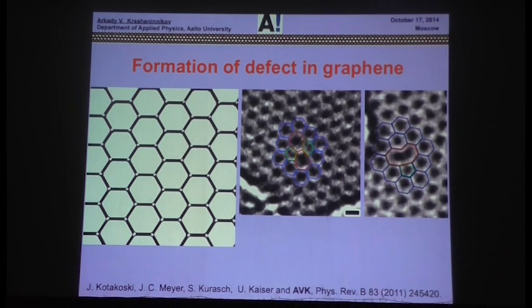Another important issue is that electrons not only knock out atoms. When you are close to the threshold, very interesting effects may happen. For example, in graphene, you may get a vacancy here, a reconstructed vacancy, where one atom is missing. You can also get the so-called Stone-Wales defect. You rotate a bond by 90 degrees.